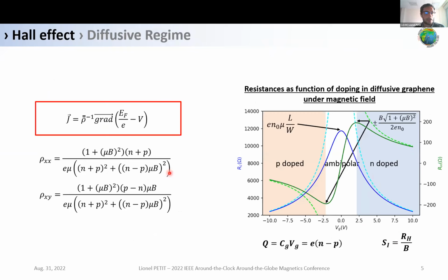But the Hall effect in graphene is more complicated than the previous model, because we have to take into account both electrons and holes. And it is what we call the two-channel model. And here are the main components of the resistivity tensor. And from that, we can plot the evolution of the main resistances as a function of the gate voltage, I mean, as a function of the doping.